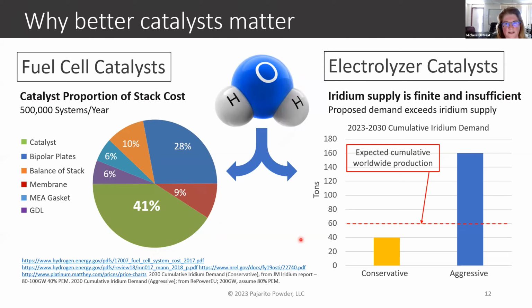And on the right-hand side, in the electrolyzer catalyst, this is specific for iridium. The iridium supply is finite and largely insufficient for the expected demand of iridium as we really move towards more fully commercializing the electrolyzer market. We expect that the cumulative iridium supply is not going to be sufficient to meet the demand. And so we are really challenged in this area to be able to achieve greater performance with our iridium oxides, either through a higher surface area, more controlled catalyst surface states, being able to thrift iridium, substituting in ruthenium or niobium, for example, and also recyclability.